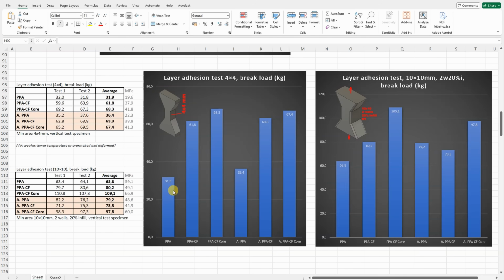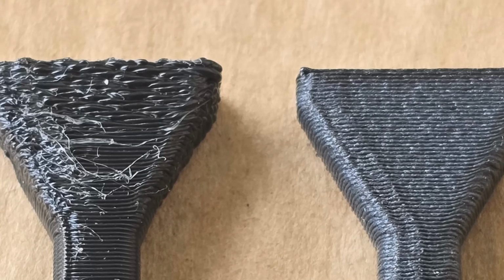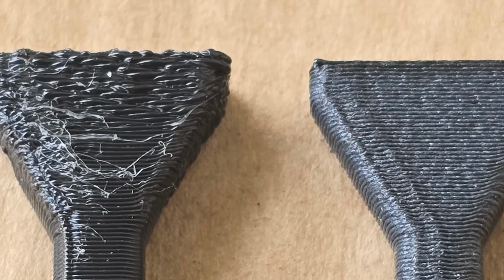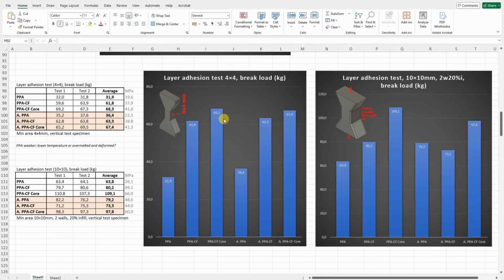Now why is the regular PPA weaker compared to the carbon fiber versions? I'm not really sure, maybe because it was printed on lower temperature, or maybe the part cooling is not enough and it was deformed and don't have nice aligning surface. Now the core version was stronger compared to the regular carbon fiber versions in both cases, but here where we have these two walls and hollow inside, it was significantly stronger, huge difference I can see here.